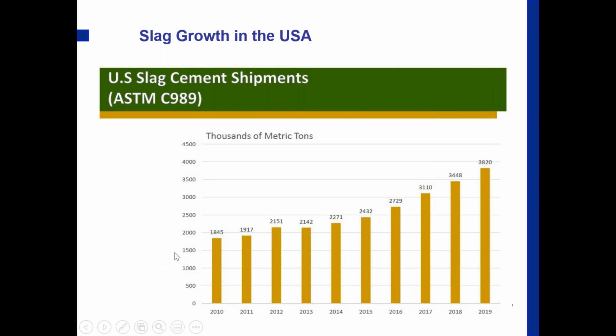I'd like to start just by talking a little bit about slag cement and specifically slag growth in the USA. As you can see, we're approaching 4,000,000 metric tons of slag with some fairly amazing growth over the last 4 or 5 years. In fact, it's fair to say we've doubled since 2010 in product and product availability. And for various reasons, I would like to think that it's mainly the high performance and the environmental concerns driving us towards using more slag cement.